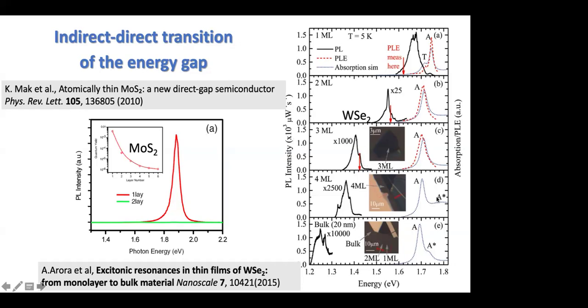This can be also appreciated on this left hand side figure, showing the luminescence and the absorption, measured in terms of photoluminescence excitation. This is this dashed line. So you can see that this transition related to the direct transition from the K point does not change its energy very much. What you really see is the effect of the indirect band gap changing a lot from one monolayer to bulk.